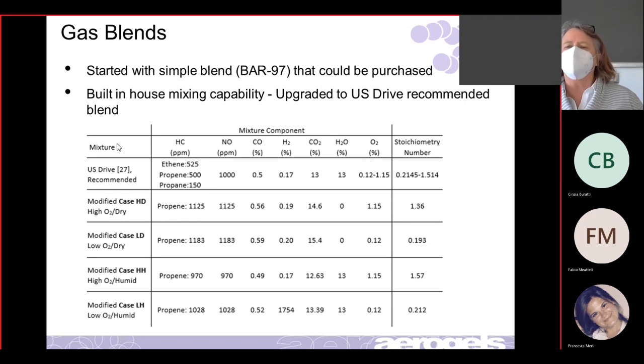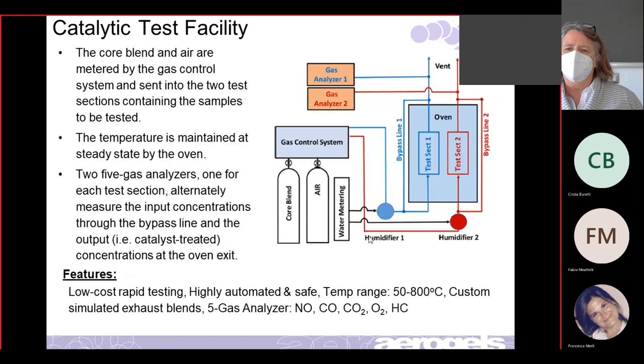We run high O2. So you can see here, 1.15% O2 versus low O2, 0.12. So there's a difference in the amount of O2. So this would be like a lean and a rich case is what it's simulating. We run cases dry. So there's no water added, no humidity. That was here where we add water. So we do dry testing and we do humid testing.